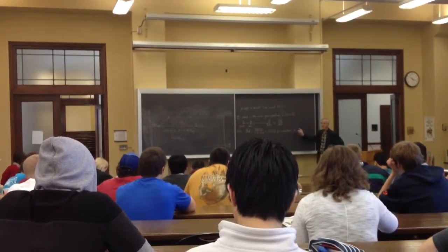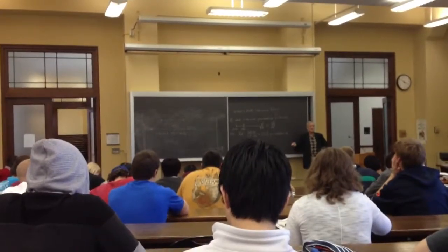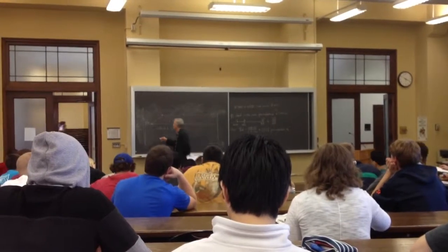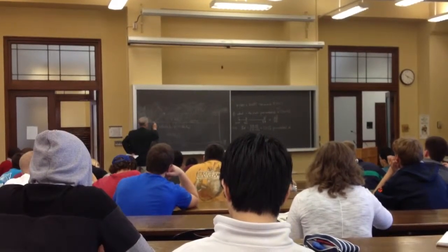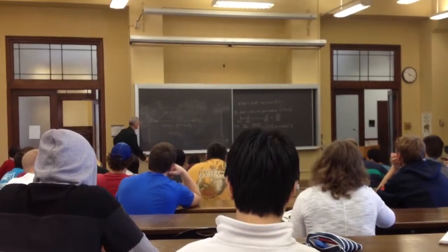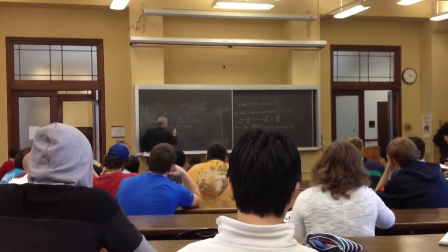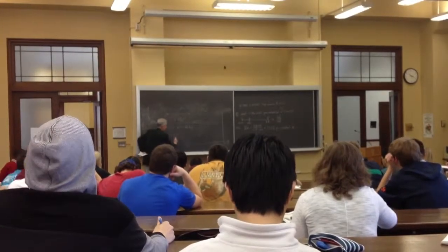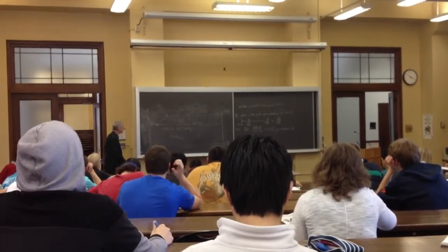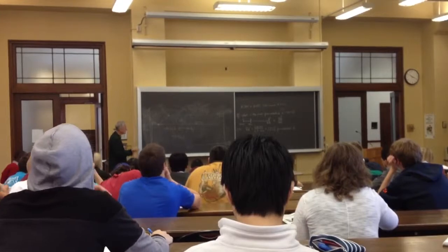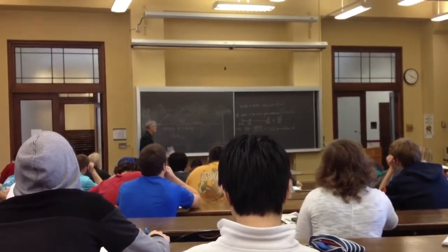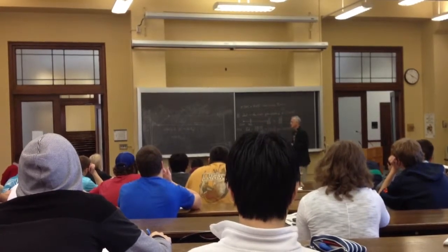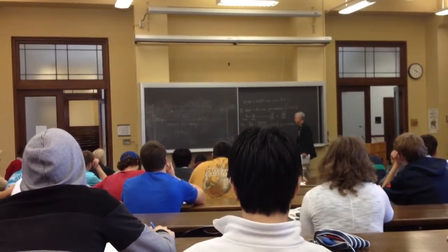Now, that's the amount of alpha that's outside of pearlite, because when you then continue to cool this down below 727 degrees centigrade, you get the eutectoid reaction, which is Fe3C, and then additional alpha comes out. And so you have proeutectoid alpha and alpha that is in the eutectoid composition, which is called pearlite. Okay?